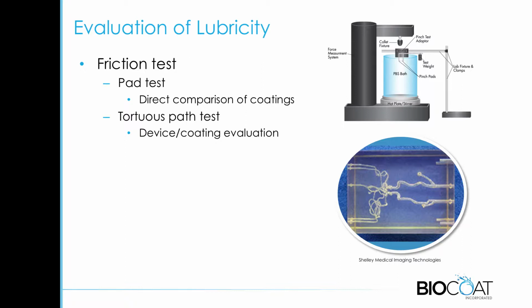For evaluation of lubricity, there's a few parts to this. There's kind of two ways of doing this. One is what I call a pad test, where you take two rubber pads, squeeze the part together, and pull it up between them under tension, usually in a hydrated solution. You're putting an applied force on, and then you're measuring the force it takes, and that should be considerably less. Best in class in a lot of these cases is at least a 10x reduction from that applied force, and even best in class is 20x. That gives a direct comparison of the different coatings and really minimizes the device design. So it's a good way of comparing different coatings,